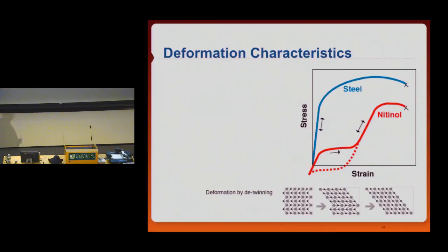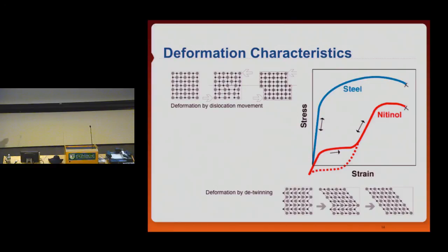I already explained, we don't have to go into the details of this thing. This strange stress-strain curve, which is not common in other materials, is caused by this deformation mechanism of detwinning, and I tried to show how that works. You have the zigzag arrangement, and then you de-zig or de-zag this thing until you only have zigs or zags, and then you have this deformed shape. If you look, on the other hand, at the deformation of steel, the really plastic deformation, you have dislocation movement, and when the dislocation has moved through your lattice here, then you have a permanent deformation there that does not go back.